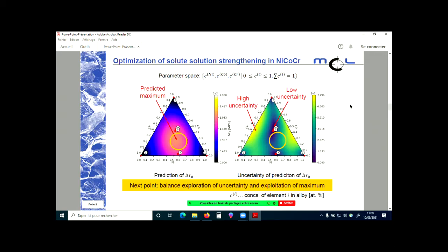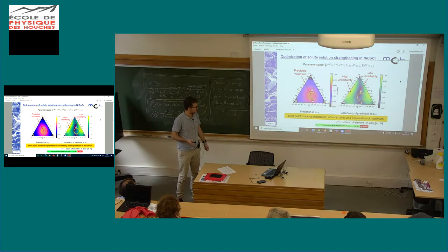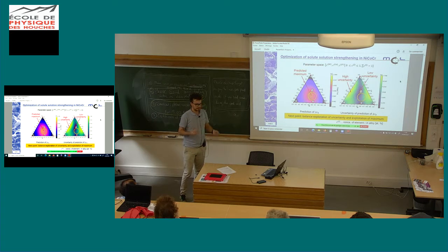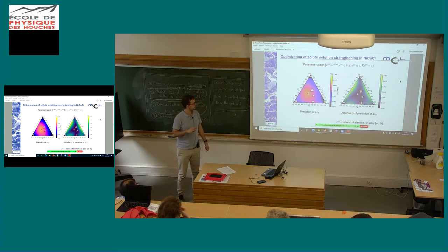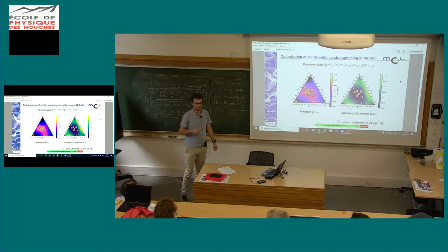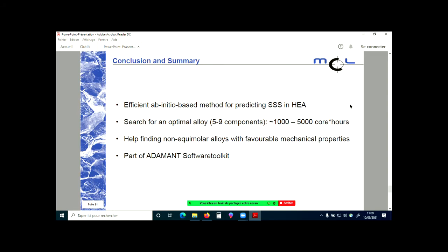Then we said, okay, let's try to find the optimal composition, and for that we use Bayesian optimization. That's basically just a way of how to optimize a function where we don't know the derivatives in a minimum number of steps. It's basically a trade-off between exploration of spaces with high uncertainty and exploitation of spaces where we know that our fit is already kind of good. So, this is basically how it's optimizing. Okay, it's not that interesting for a 3-component alloy. I mean, one can argue one just makes a grid. But this is really important if I want to do it with 9 components or even more, or if I want to put some constraints on it.